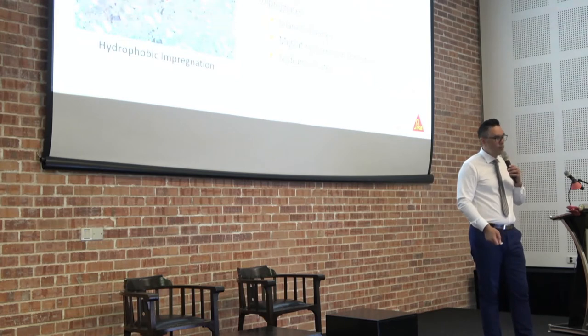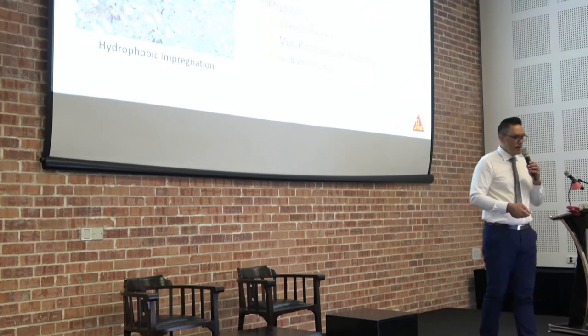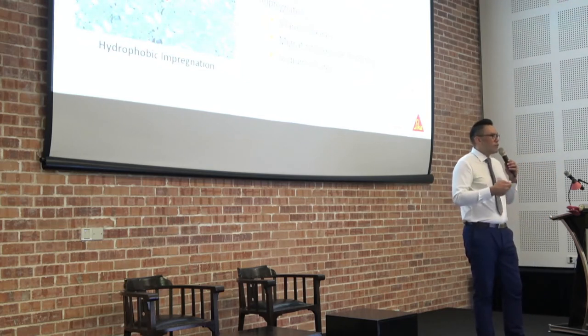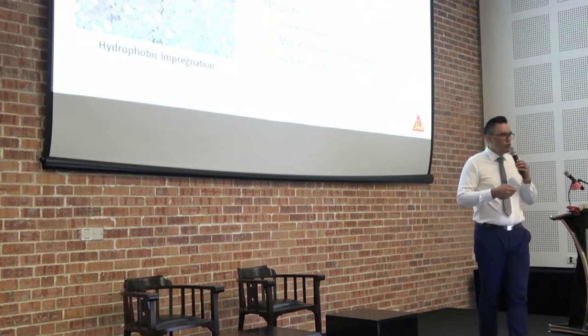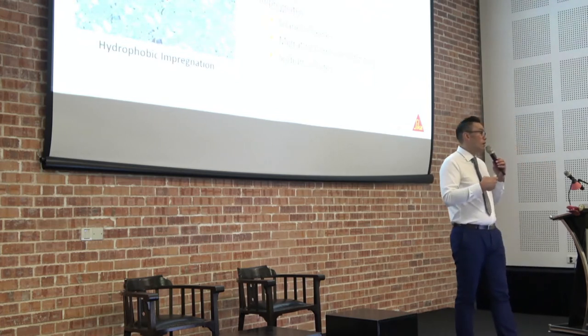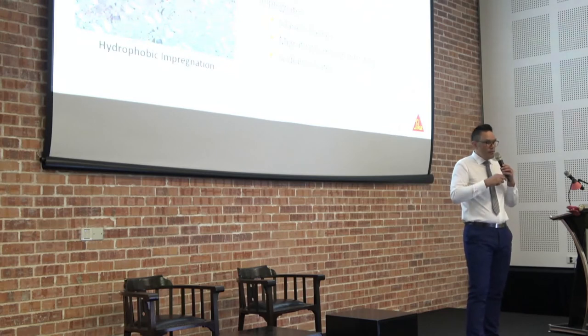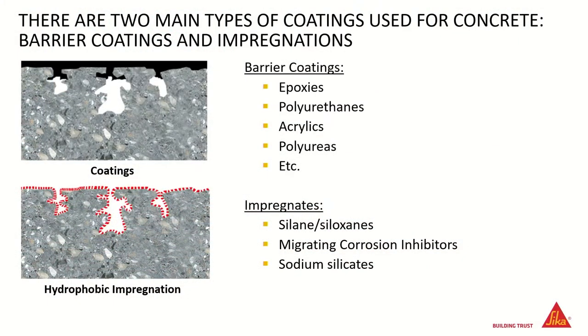The second type that we were talking about earlier is the hydrophobic impregnation, or the impregnates. They are a different type of penetrating molecule, a silane or siloxane based chemical that sets up a little micro surface repeller. We also have what we call migrating corrosion inhibitors to protect our reinforcement, and then we have sodium silicates. So it depends on your concrete, and it depends what you want to protect against. The difference is quite clear.